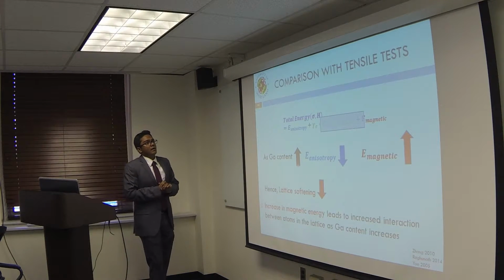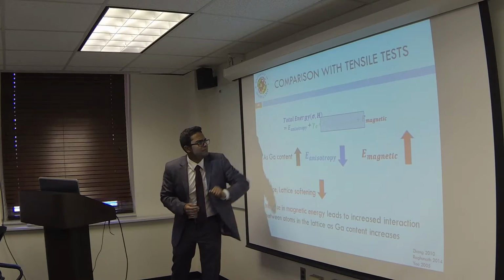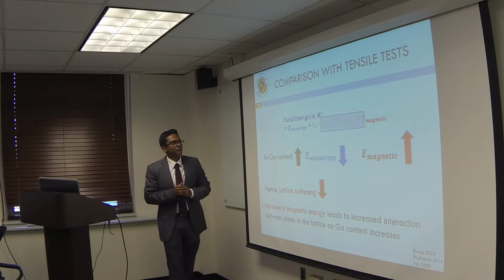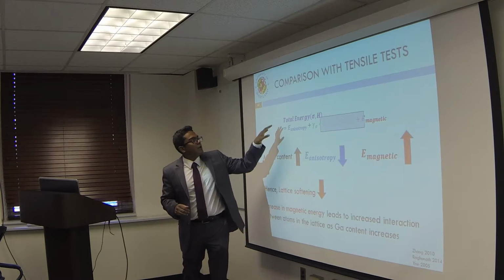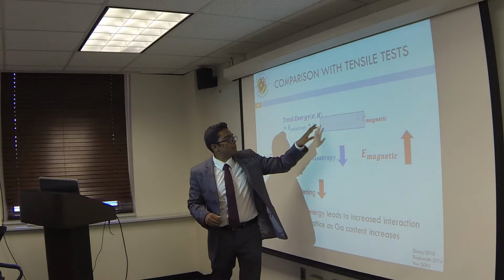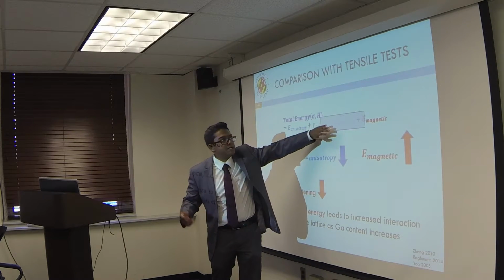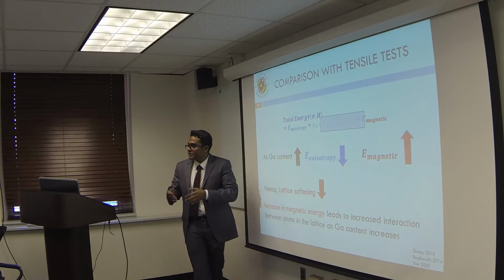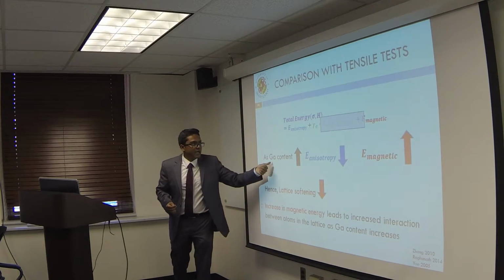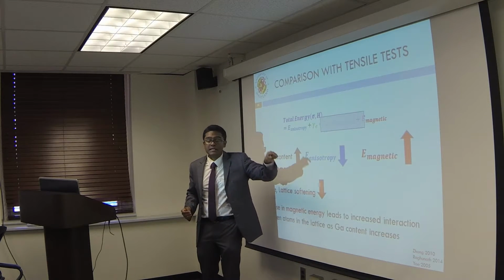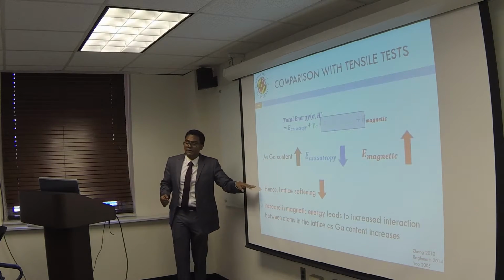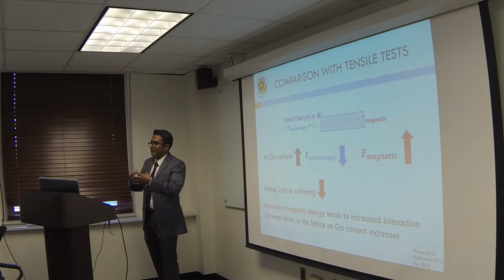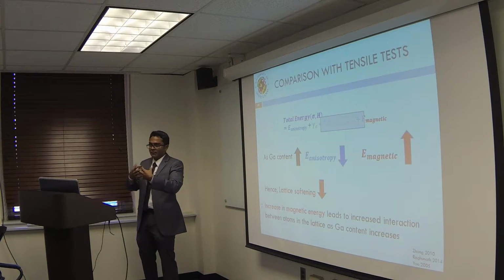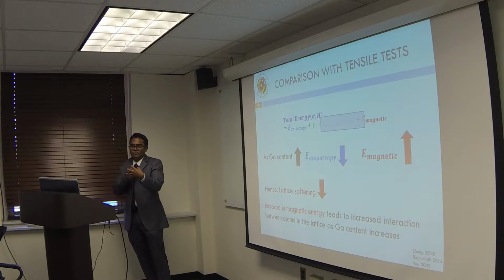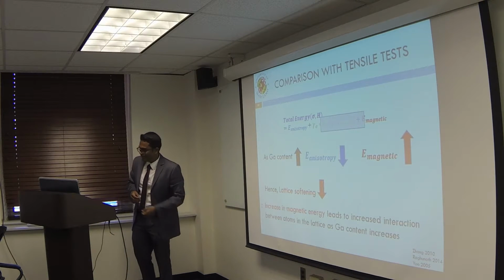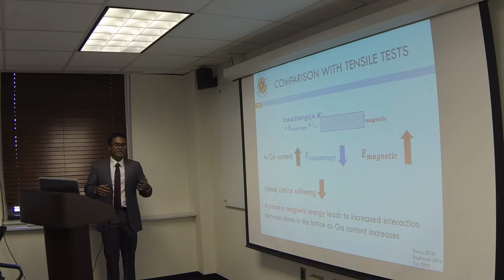But what happens when I apply magnetic fields? For some reason, the boxes are offset by a little, but never mind. Anyways, the total energy is still the same, but since we don't apply any stresses, we don't have any magnetoelastic energy, and we have magnetic energy going into the system from the applied magnetic fields. So as the gallium content increases, anisotropy still decreases, and the magnetic energy increases, and this restricts lattice softening, because the more magnetic energy there is in the system, the more the atoms interact with one another and try to stick together, and that increases restriction of lattice softening.